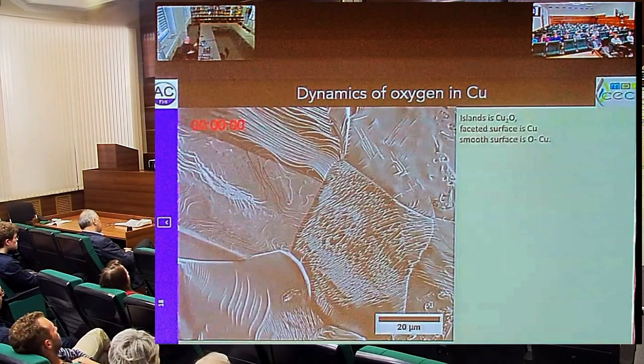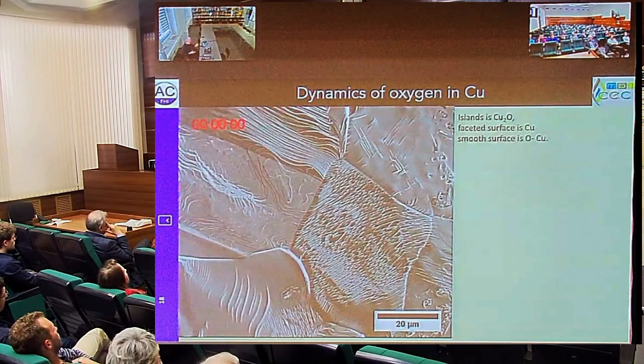And now we put this into a temporal evolution under reaction conditions that are typical for methanol synthesis, and you will see a dot, and then you can observe what the surface does. So if it's truly dynamic, and you see that the interface is completely changing backward and forward, then this reaction is driven by an oscillatory process between copper oxide and copper plus oxygen. And that explains, of course, why the zinc oxide can never be fixed on the surface, because the surface itself is moving that way, and the zinc oxide will always be shaking around.